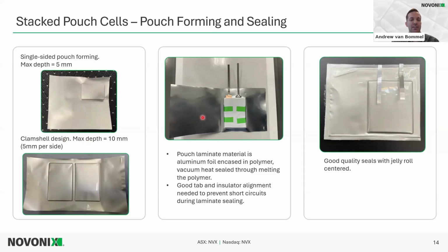So in this case, if the stack is placed inside the pocket, it can extend a little bit so then the other side also has a pocket to encase that stack. So the pocket has to be made so that there's good alignment of the tab and the insulator. So there's an insulating piece that melts on the tab, and also the pouch material is melted too during the sealing process. And this ensures that there's good sealing all around the pouch material.